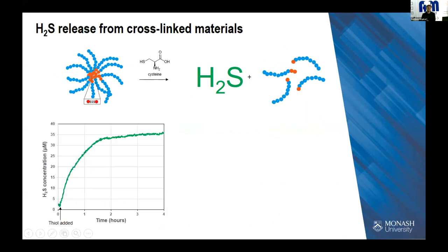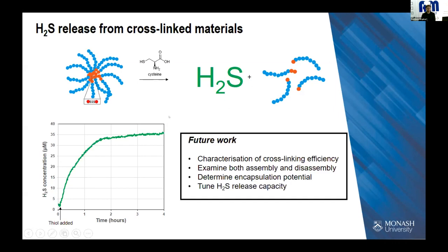React this with cysteine to release H2S. And quite pleasingly, we see that we have a release profile which is consistent with trisulfides being in the core of the assembly. So that's where this work is at the moment, and we've still got a bit more work to do. However, it's promising early results. So we're going to look more closely into characterizing the cross-linking efficiency of Bunte salts, examining both the assembly and disassembly, looking to determine encapsulation potential of maybe some chemotherapeutic, and looking to tune this H2S release capacity.